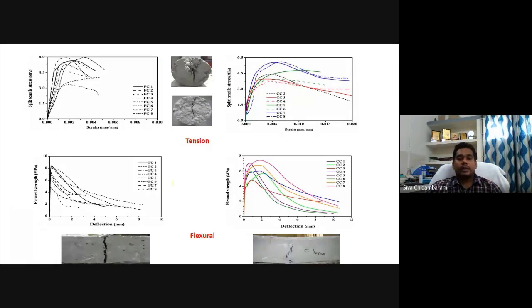here the difference is that in fiber reinforced concrete, it goes and it degrades. When it comes to fiber reinforced cementitious composite, it keeps on going like this and degrades like this. So the amount of post-strength retention capacity varies with respect to fiber reinforced concrete. For example, if I take this level, you can see at this point it has failed, and at this point it has failed. So the difference decides the ductility, toughness, damping, etc. So this is the advantage of fiber reinforced cementitious composites.